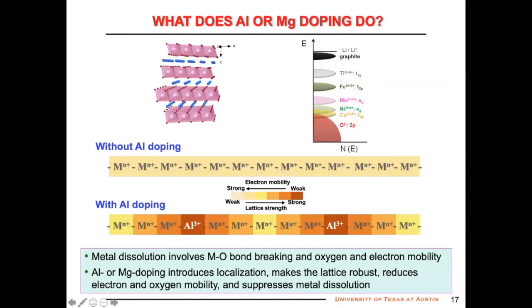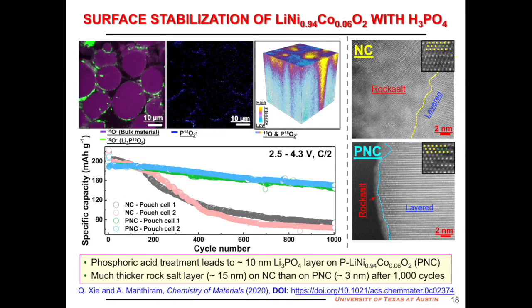As soon as you put aluminum, you perturb that electron delocalization or communication. The lattice becomes a little bit more localized, the so-called Anderson localization, as the physics community calls it. Because it becomes robust, the metal-oxygen bond becomes stronger, and electron mobility is decreased, therefore metal dissolution is decreased. So far I talked about doping, bulk stabilization.